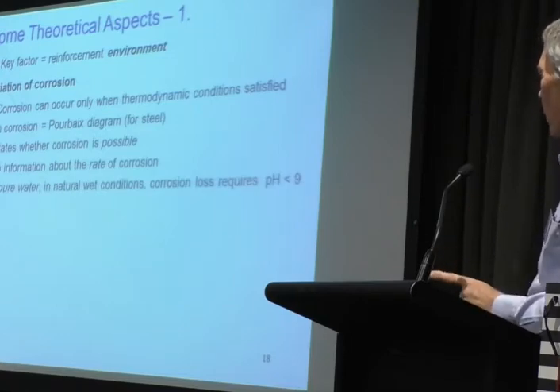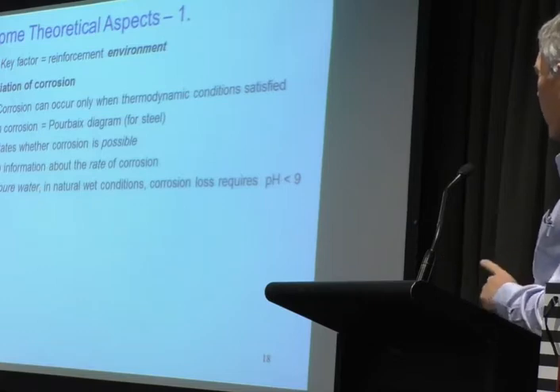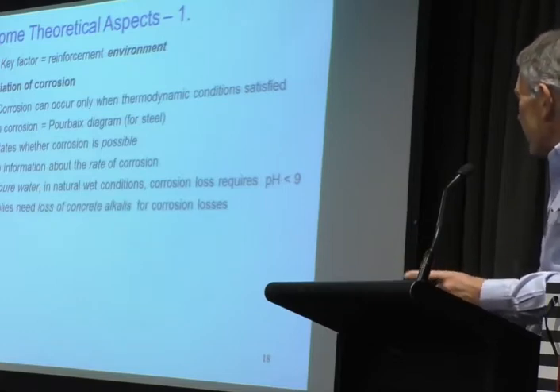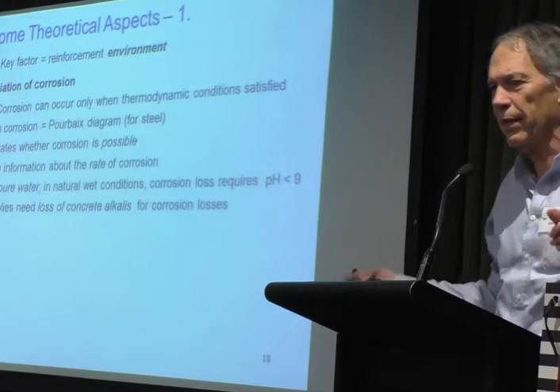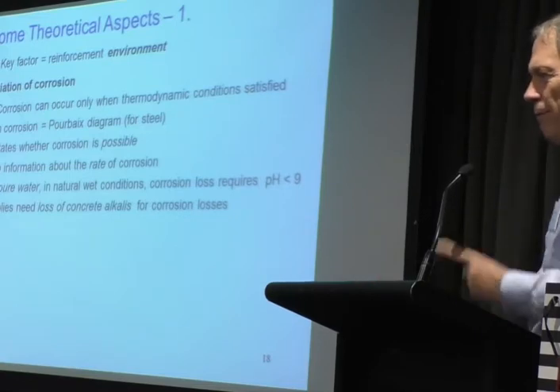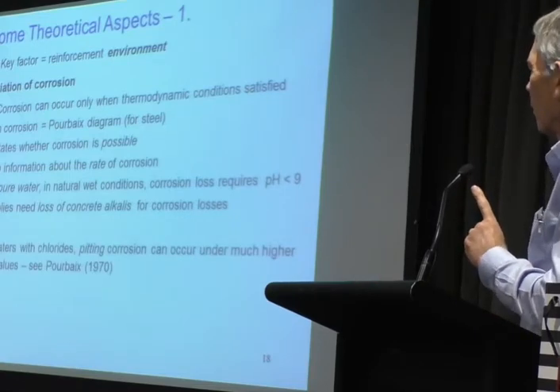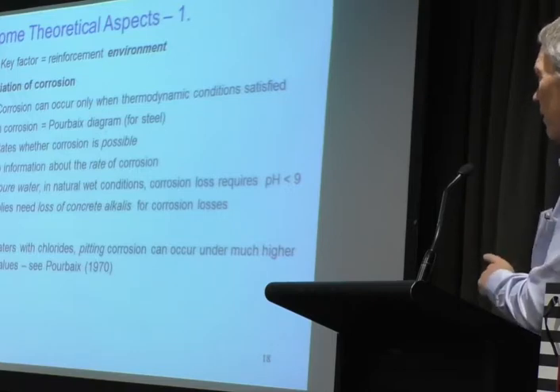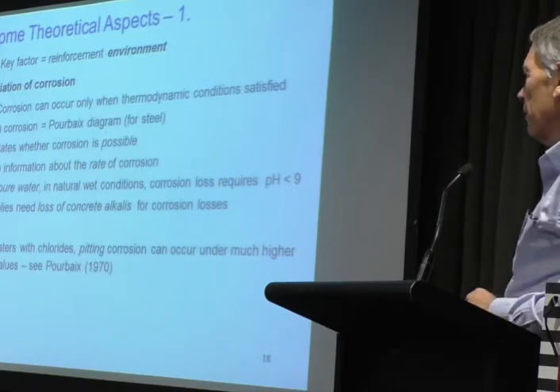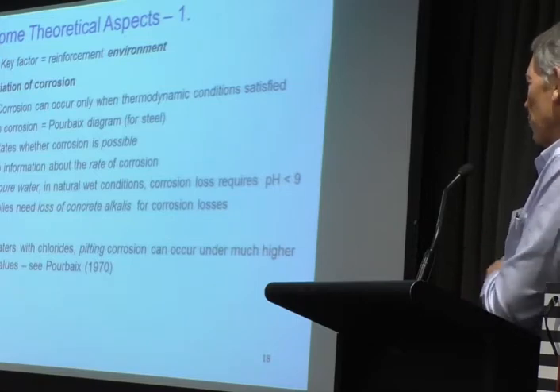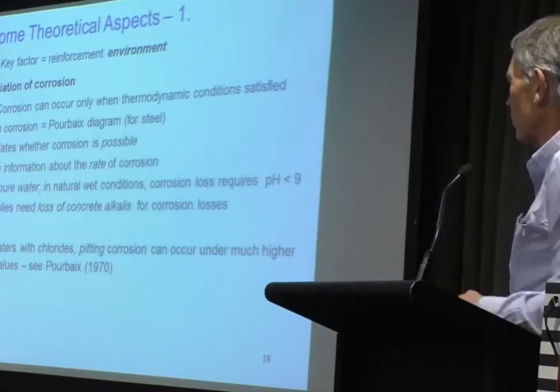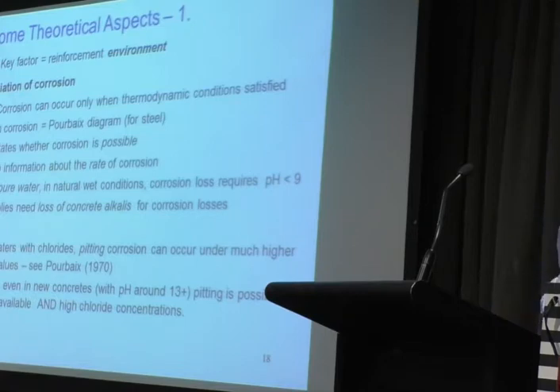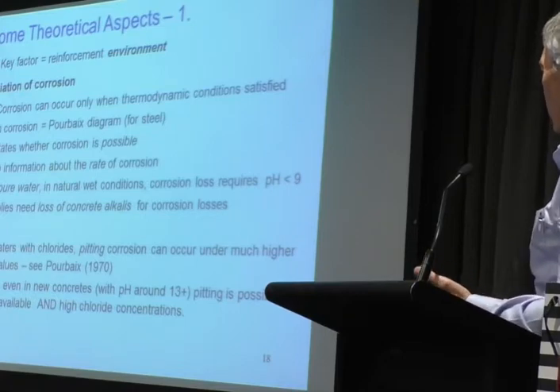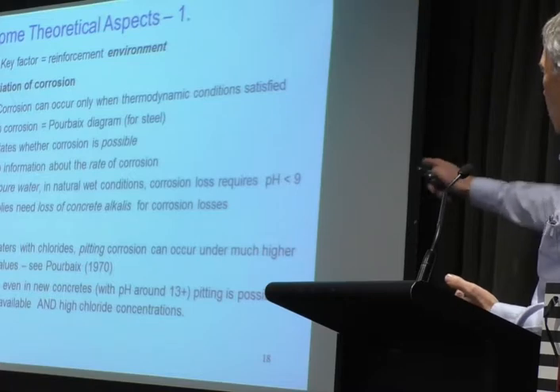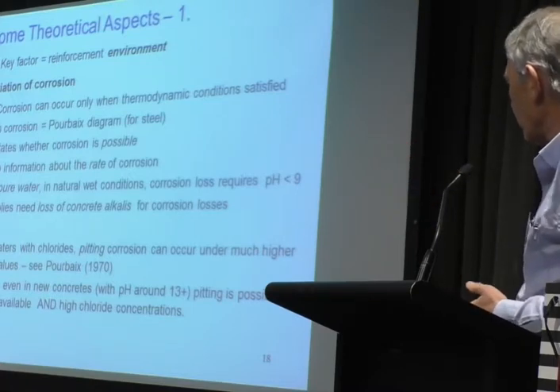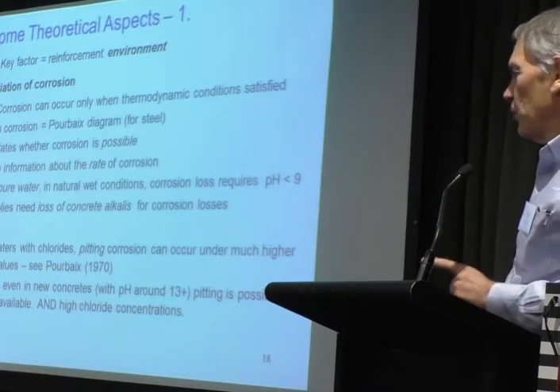And in pure water, in natural wet conditions, it requires pH less than 9. Now that implies that somehow or other we've got to get rid of some of the alkalinity. Otherwise nothing will happen, except when we have chlorides present, we can have pitting. And you can read about that in Pourbaix's 1970 paper. So there's a difference: pitting versus overall corrosion loss. And even in new concretes, we know that pH is around 13. It is possible, according to Pourbaix's 1970 paper, to have pitting, but you need oxygen.